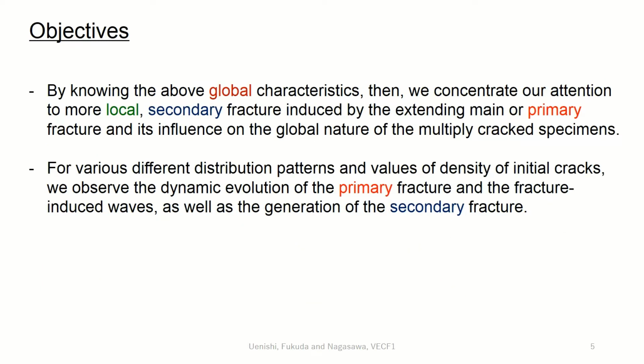By knowing the above global characteristics, then, we concentrate our attention to more local, secondary fracture induced by the extending main or primary fracture and its influence on the global nature of the specimens with multiple cracks. For various different distribution patterns and values of density of initial cracks, we observe the dynamic evolution of the primary fracture and the fracture-induced waves, as well as the generation of the secondary fracture.